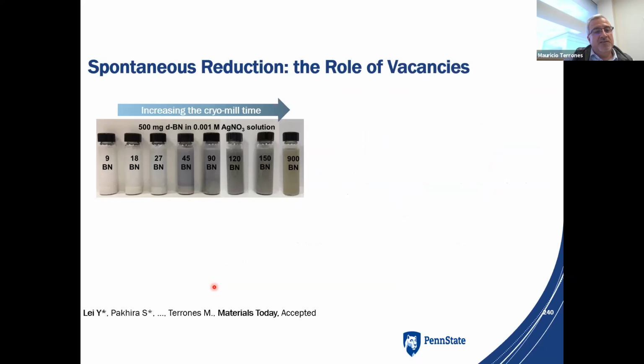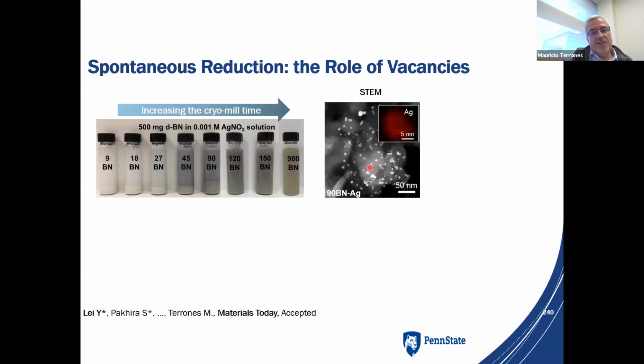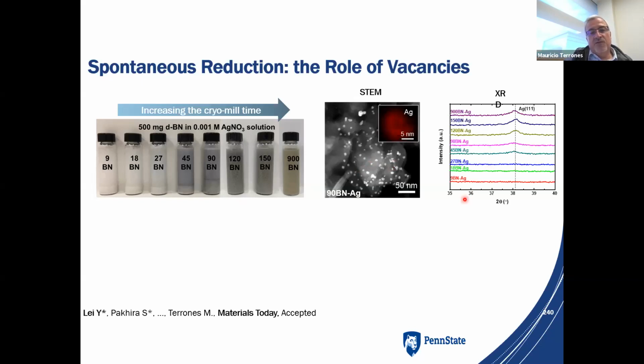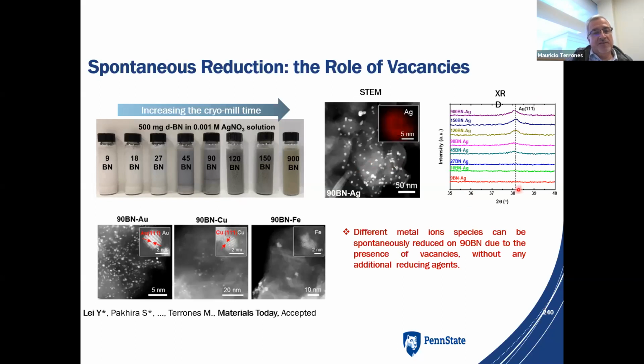So one thing that we did, and this is just for the chemistry part of this work, is that this is the cryomilling time, 900 minutes. And then we can reduce silver nitrate, and we can see here a sort of brownish solution, and that's because you are reducing the nitrate into silver nanoparticles. So when we look at the system, you can see the silver nanoparticles very well anchored. If you do an XRD, you can see these beautiful nanoparticles, but you can do it with gold, with iron, with copper. So we are making a boron nitride system that is reactive,